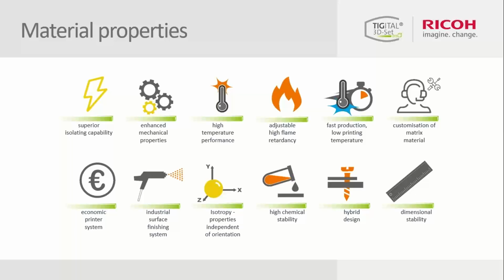And one key point is also the hybridization of our materials. That means you can directly use endless fibers like carbon fibers or glass fibers to improve the mechanical properties of the parts and combine these systems, or you can also use a metal part or a drill so that you can directly drill the parts because of the high mechanical properties. So it's not creeping, it's not changing the whole part system, and it's not getting melted anyway. So hybridization is really easily done with our materials.